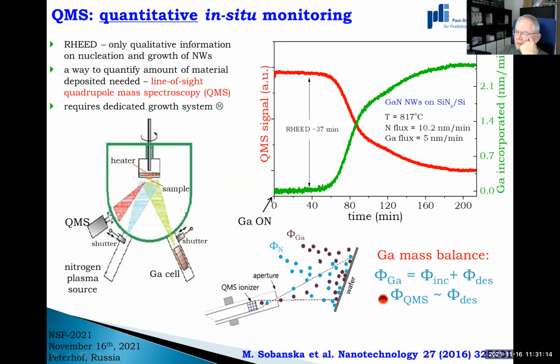But since we know exactly how much gallium we deliver to the substrate from the simple mass balance, we can calculate the amount of gallium that was incorporated into the crystal. This is this green curve. So the process is like that. When we start growth and we open the gallium cell, at the beginning there's no incorporation of gallium into the crystal at all. Then incorporation increases, meaning gallium nitride starts growing on the surface, and then there are next steps. I will explain them in a moment.